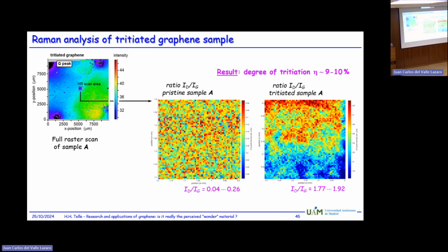But at all the other parts, you see that basically there is some signal you're seeing, which is relatively homogeneous, and you see a few points here which are exactly similar to the ones I've shown for the pristine graphene, which are basically dust particles which had accumulated on the sample. So if you now home in into this central part, for example, and do a scan before tritiation and after tritiation, we actually see that the pristine sample is more or less homogeneous, whereas the tritiated sample is less so.